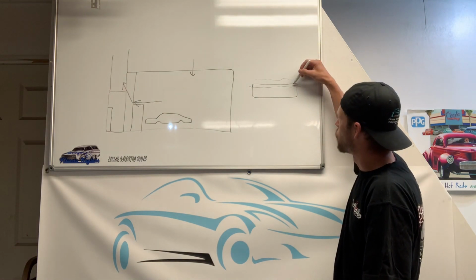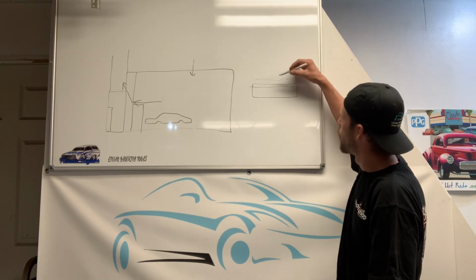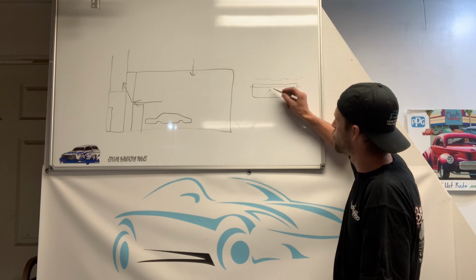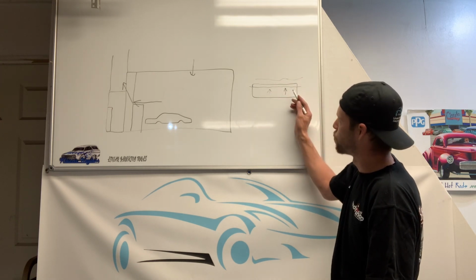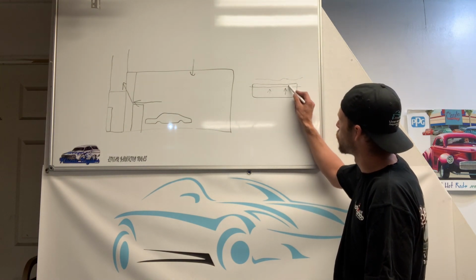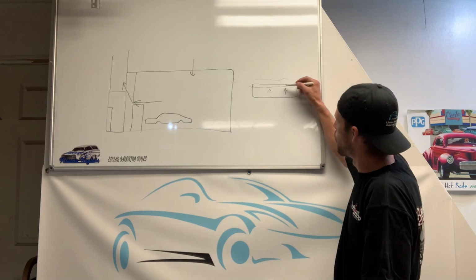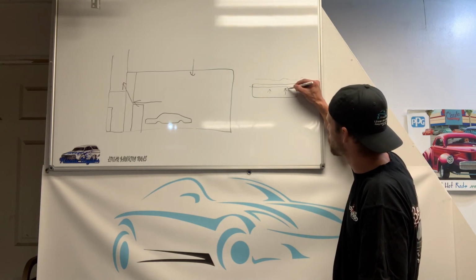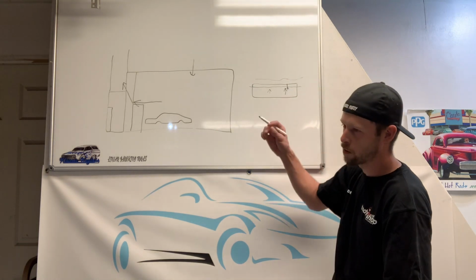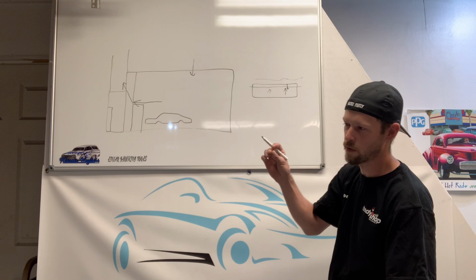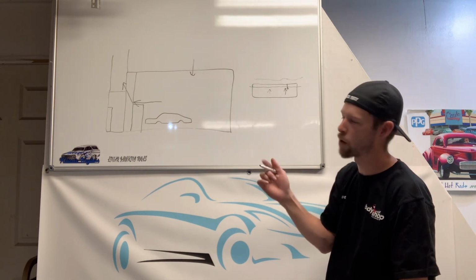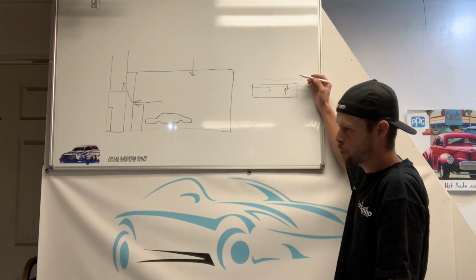So basically what you're doing, this is skinned over, and there's these solvents down here that are still trying to get out. This is not dried yet, and these solvents are trying to get out, but this has skinned over. This is getting hard now, and those solvents have nowhere to go, so eventually they all collect in one spot and they push out, and a lot of times it'll look like a little fisheye or something, and you may even see some liquid coming out. That's solvent, that's reducers, basically. And that's one reason why solvent pop happens.